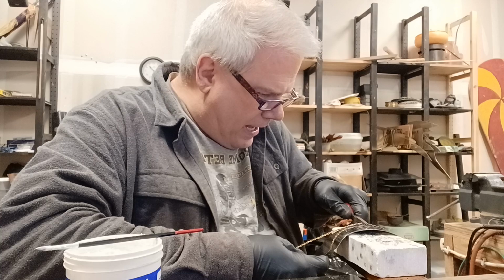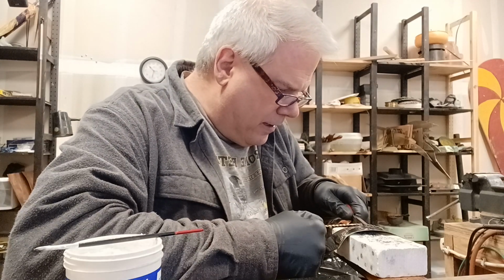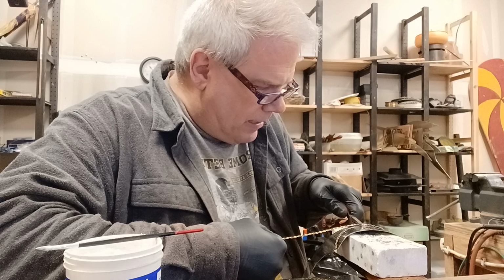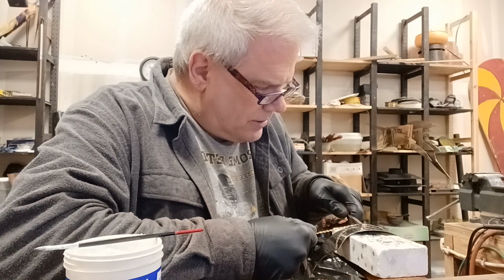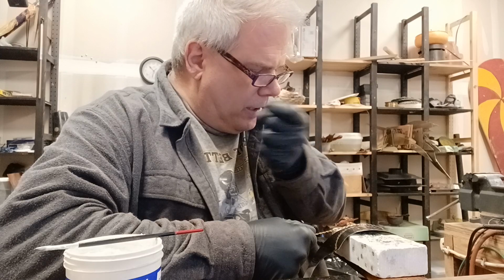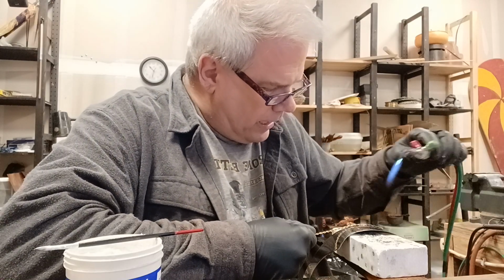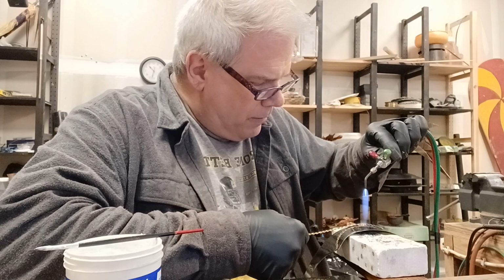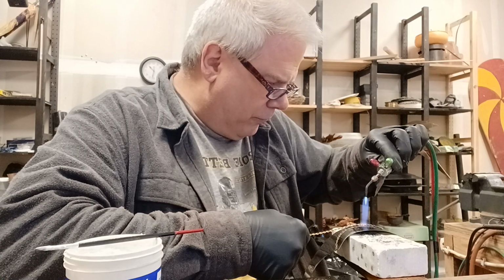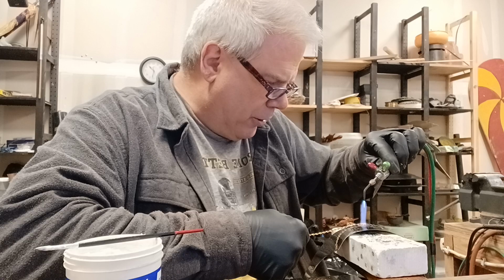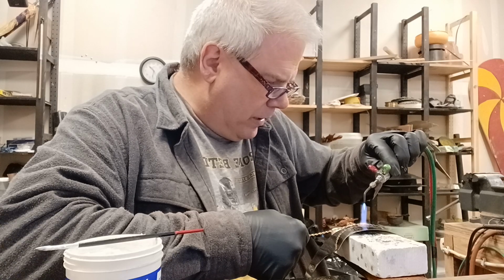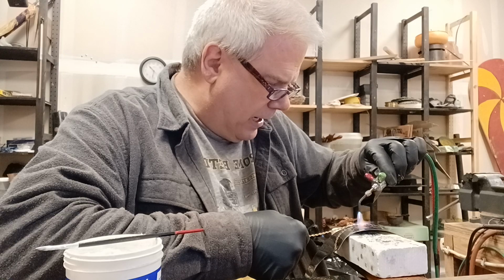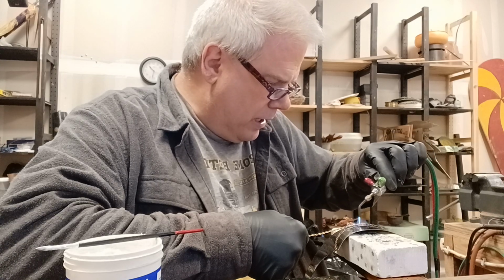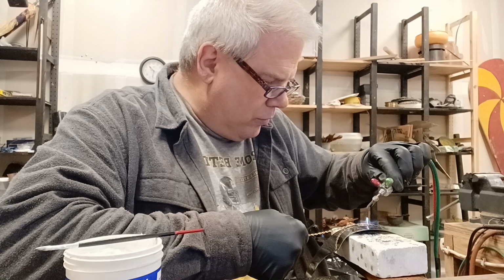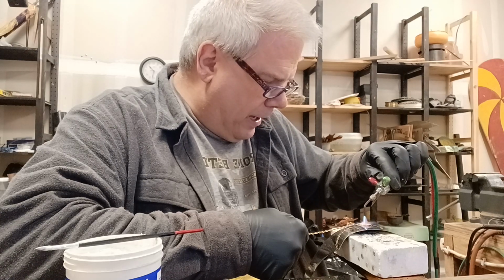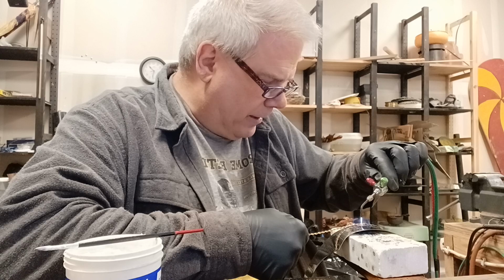And I can also see that as the brass rod is softening from the heat treatment, how I said that it kind of anneals as you're working, the weight of the rod over there in the distance, I'm not looking at the camera, so I'm just guessing you can see what I did, is pulling down on the rod and making a bigger gap appear between the rod and the nickel, and the rod is not in contact with the solder anymore. And so I fixed that by supporting the weight of the rod with my left hand.